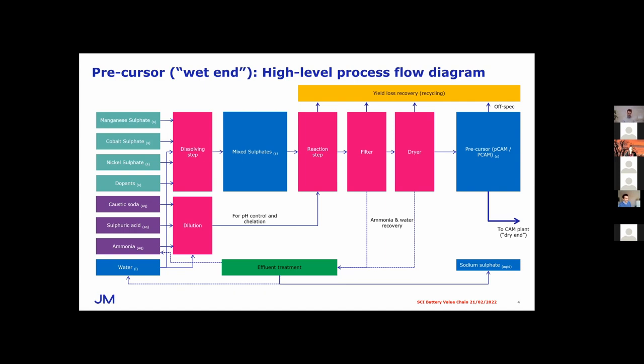And that material is then sent on to the dry end of the facility, which is where you form your cathode material. We'll see that on the next slide. One of the key outputs from this process, because you're converting from mixed sulfates to hydroxide, is that through the reaction you produce sodium sulfate, and this is typically stripped out in your effluent treatment plant, where you also aim to capture the ammonia, which you can't emit to the air, and also recover as much water as possible to put back into the system to dissolve a lot of those salts that are coming in crystal form.